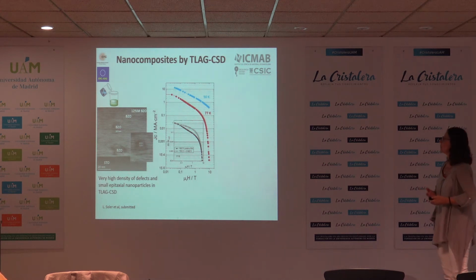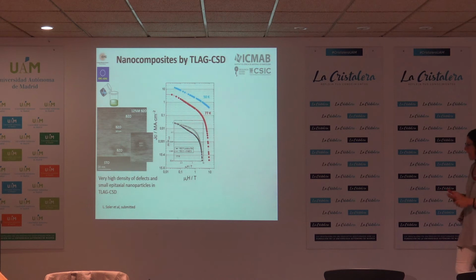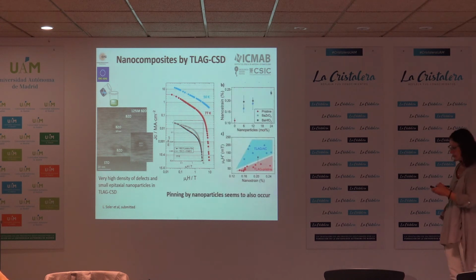So at the end, what we have been able to see is that it's not. We are able to get nanocomposites with quite nice, small nanoparticles with this process. We can also see that we can get higher performances with the nanoparticles. In fact, we also generate a lot of stacking faults, all this intergrowth that I mentioned before. So we have small nanoparticles, plus also the nanostrain that we had induced by this intergrowth.